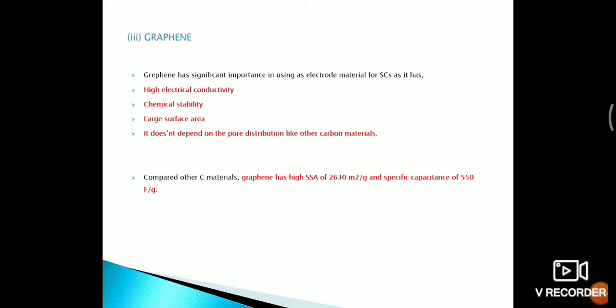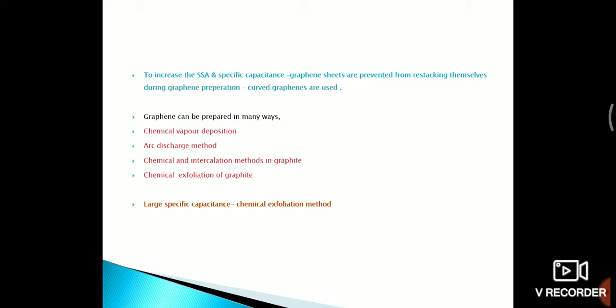Graphene has significant importance as an electrode material as it has high electrical conductivity, chemical stability, and large surface area, and moreover, it doesn't depend on the pore distribution like other carbon materials. Compared to other carbon materials, graphene has a high specific surface area of 2630 meters square per gram and a specific capacitance of 550 farad per gram. To increase the specific surface area and specific capacitance, graphene sheets are prevented from restacking themselves during graphene preparation and consequent electrode preparation.